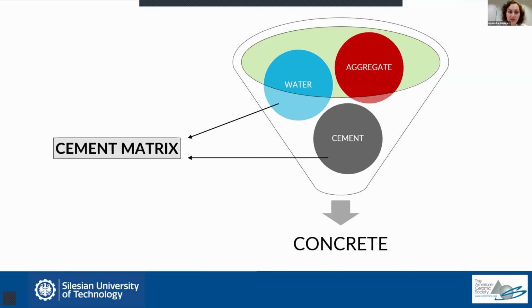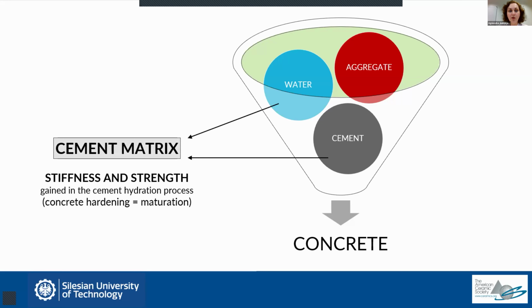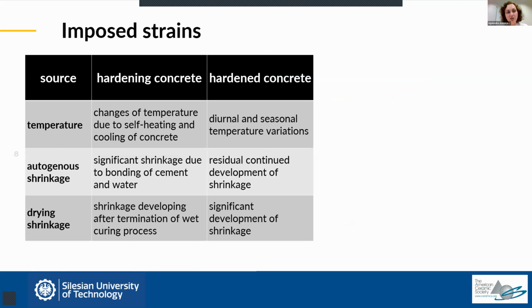On one hand, this is how we obtain this artificial stone. Because of this hydration of cement and water and production of the cement matrix, we obtain a desirable stiffness and strength. So that is actually our goal. But at the same time, we usually forget that this process has some negative effects. Due to the hydration, there are some phenomena that happen in concrete, which are related to temperature and shrinkage.